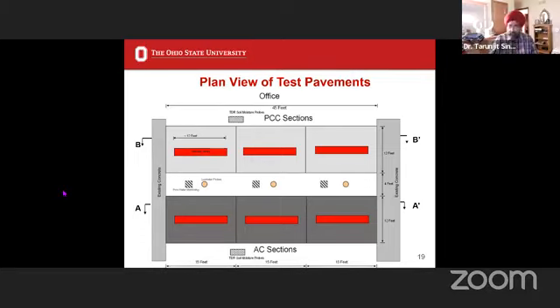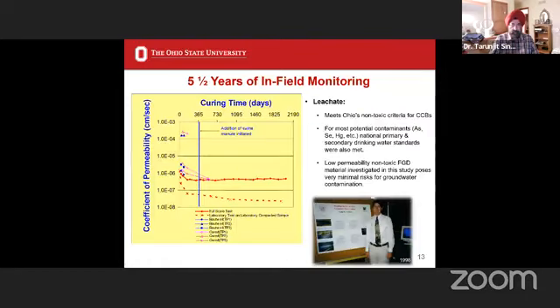Sure. Let me go back to you there. As many of you are aware, in geotechnical engineering, it is well understood that because it is very difficult to measure field permeability, we give ourselves a factor of safety of about 10 when it comes to permeability. So if in the field, I want a permeability value of 10 to the minus 6 centimeters per second, because measuring in the field is so difficult, what we generally use, somebody is drawing on there, that wasn't me, but don't worry, is that we generally take an order of magnitude lower in the lab.